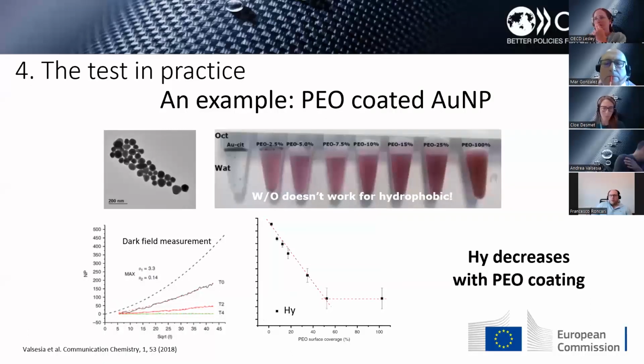Our characterization method was first applied to gold nanoparticles coated with polyethylene oxide, and all the results were published in a paper from 2018. As you can see at the top of the slide, the water-octanol partition coefficient doesn't work for hydrophobic nanomaterials because they tend to aggregate at the interface.